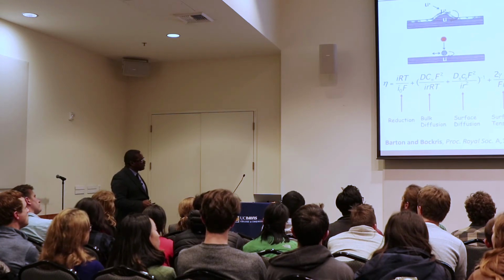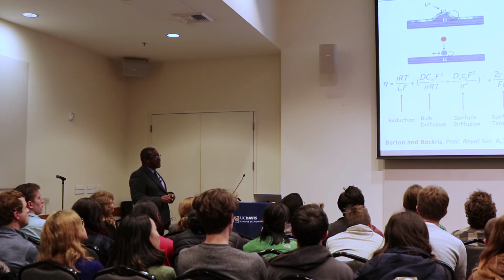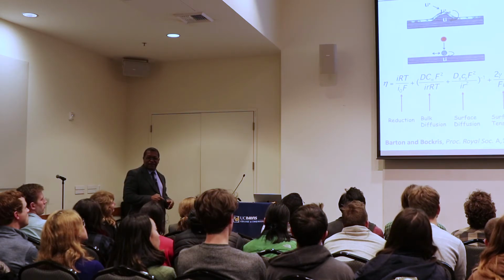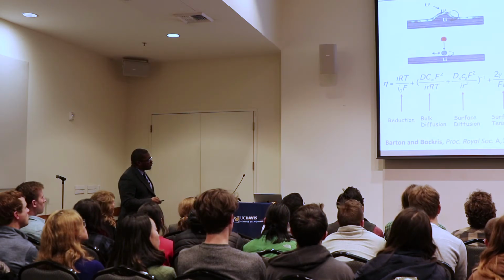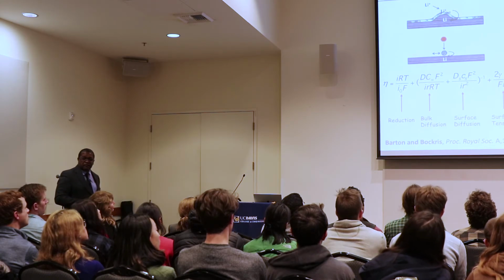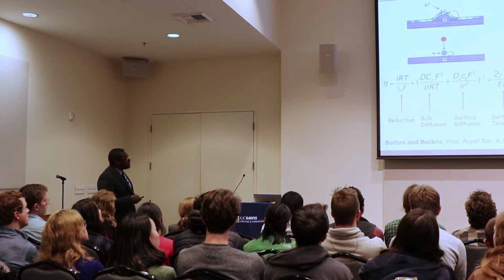So we did a lot of fancy things. The question was, how do we verify this, how do we measure this? It turns out there's a very old theory by Barton and Bockris that tells one how, by measuring the overpotential during the early stages of deposition, you can get out physical variables like the real surface energy.